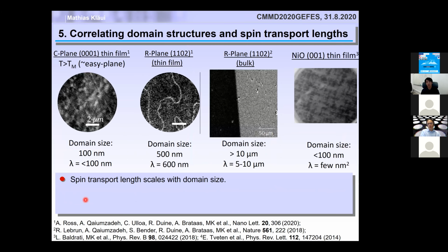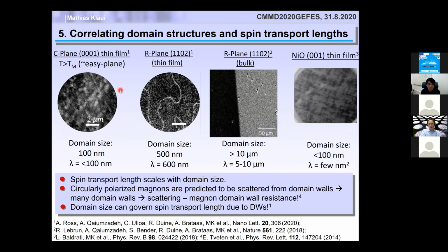So we think that one of the things that is important is homogeneity of the material, because even in an antiferromagnet, there is no advantage in the energy of forming domains. You have an increase in the exchange energy. So fundamentally, the single domain state should be the preferred state. And this is what we see in these most perfect single crystals here. I think the reason that the domain sizes differ has to do with growth, misfit dislocations. That's one of the things, because due to the strong magnetoelastic coupling, a small change in the crystallographic structure leading to small strain will lead to large anisotropy changes. So that's one of the things.